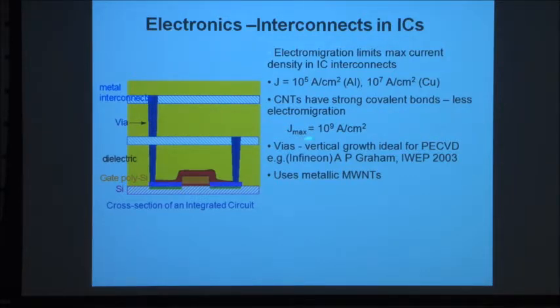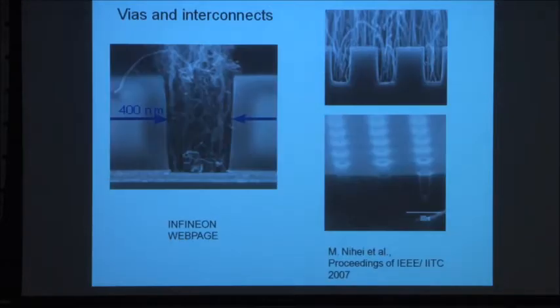What you've got to note, however, is read the papers correctly. This 10 to the 9 is if you actually grow nanotubes under the perfect condition for growing nanotubes. It's maybe about 900 or 1,000 degrees C. If you try and do that in the back end of a logic or a memory device, you kill all the logic in the memory. So although in theory the CNT has a really good current density, at low temperatures it may not.